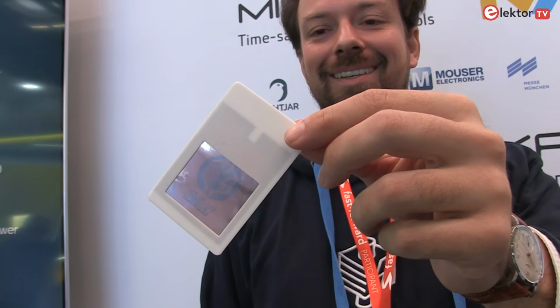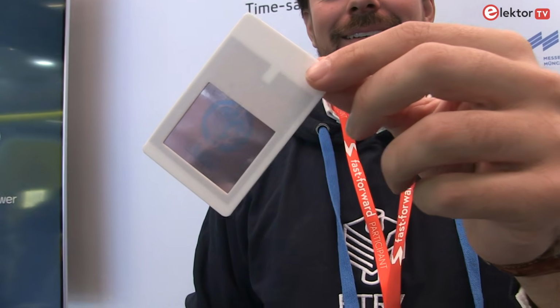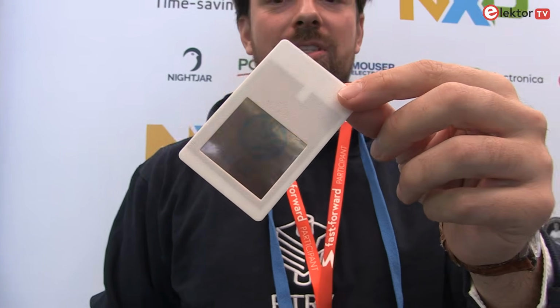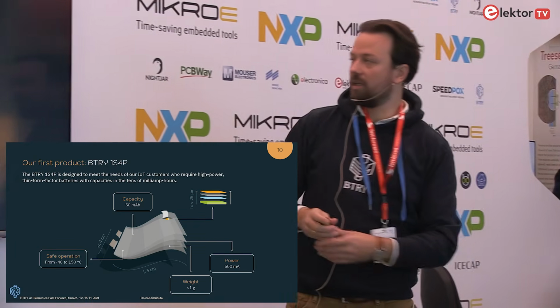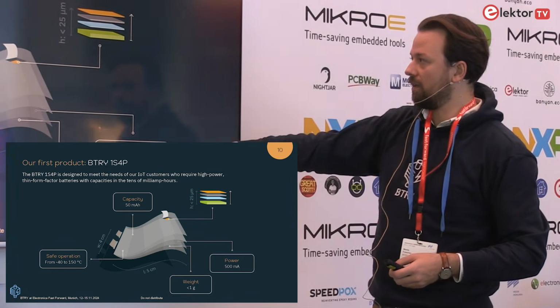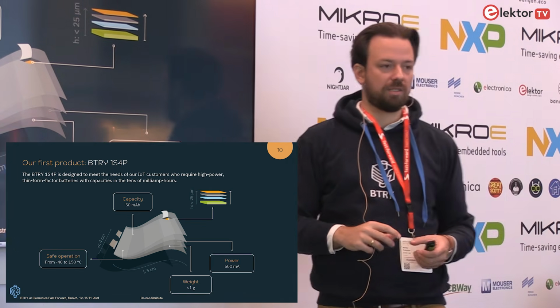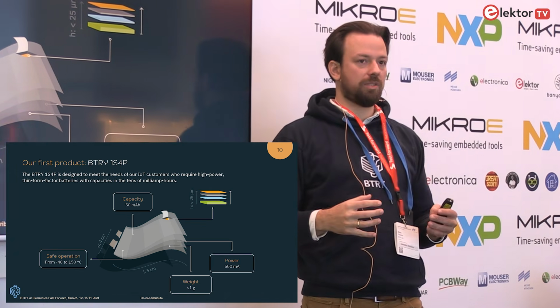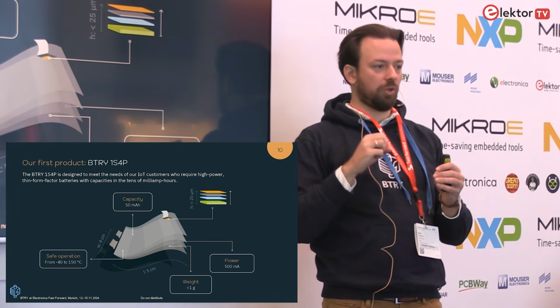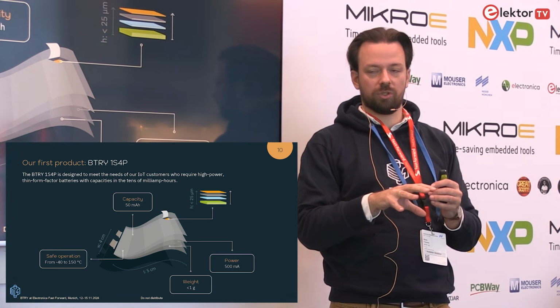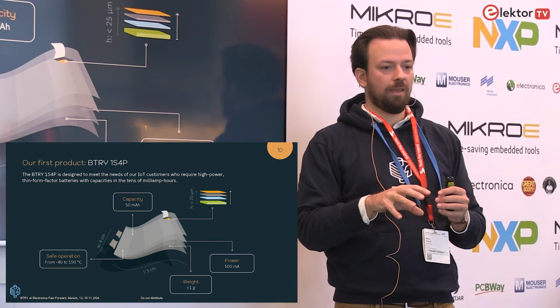It has a capacity in the order of 50 milliamp hour, which is enough for most sensor applications. But importantly, it has a very high power ratio, so in this case it can deliver 500 milliamps with the same battery. This allows you to measure signals, but you can also send signals for different protocols, for example, LoRaWAN.